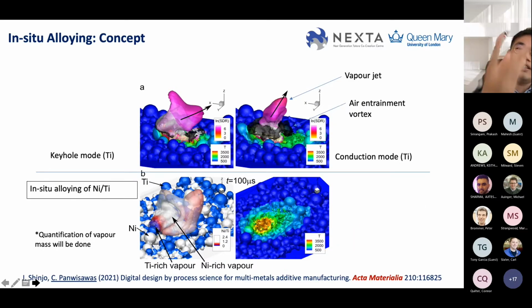So once we understand the elemental behavior, we want to mix them together now. The challenge is quite high because we have a lot of things we don't know, for example, the interaction term and interfacial energy. But we want to use some kind of traditional rule-of-mixture assumption to go further to the in-situ alloying of these two materials. For example, in this system, we have a nickel-titanium alloy, where you can quantify the vapor mass or mass loss from a pit as a function of a process parameter. And we can quantify the vapor mass as well. And this is a very important step for us to understand how things mix together.